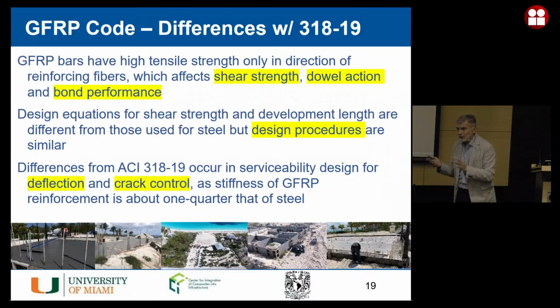Because you have a material that, if it conforms to D7957, has a modulus of elasticity of 47 GPa, 47 gigapascal. Steel is 200. Okay, the new generation bar is 60 GPa, but still, you could say, basically it is less than 1/3 of that of steel. So you have to account for that.